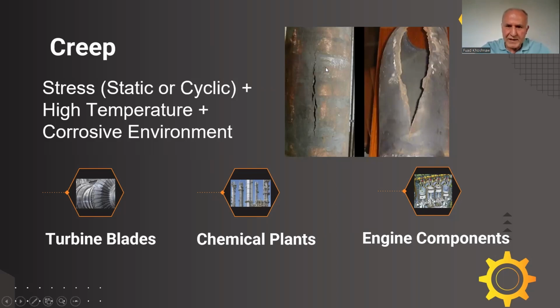So this is one of the case studies from the book I mentioned in the beginning, and Yolanda mentioned. You see it is cracking, but the crack shown here is not a fatigue crack. If you do fractography with a scanning electron microscope, that will give some details about what type of cause it was. Is it temperature or only cyclic stress?